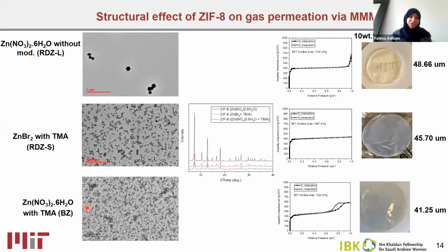So the same conditions have been applied for all of these materials, but if the material consists of only microporous, it would give this kind of isotherm. However, if there is ultramicroporous, we will get this type of isotherm, which is the same isotherm type 1 for microporous materials. And if we have both, we're going to get a combination isotherm.